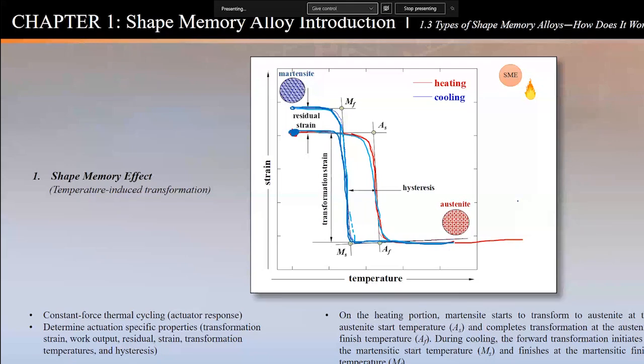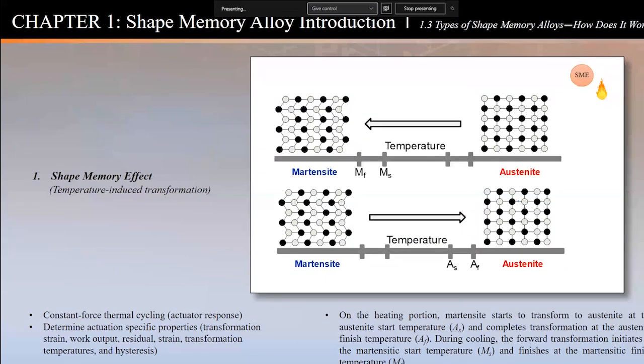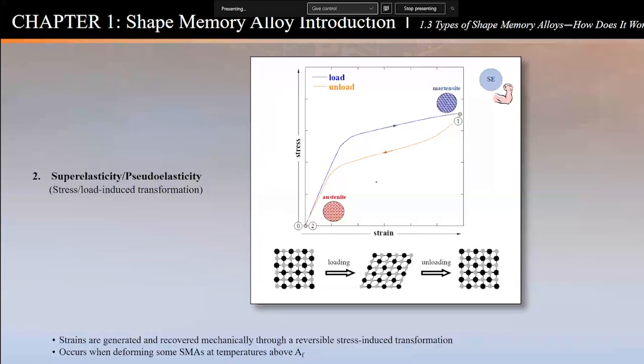This is just in a cartoonish way what it looks like between temperatures. Again, when I'm heating, I go through austenite start and finish. It goes to the austenite phase. And then when I'm cooling, it goes to martensite start and finish, and it goes to that lower symmetry twinned microstructure. Now the second type, so the first type is shape memory effect. I can change the material by applying heat. Not always the same. You can do it also by what's known as superelasticity. Some call it pseudoelasticity. I refer to it as SE. It stands for superelasticity or pseudoelasticity, and basically it's a